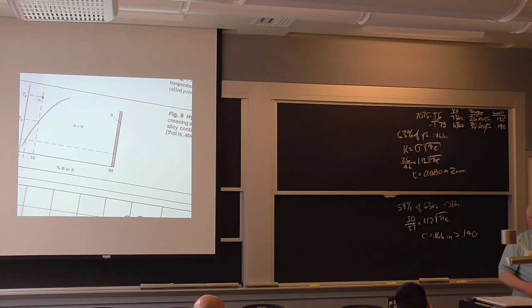If you just change over heat treat to get better corrosion resistance, better toughness, but lose yield strength, increase the wall a little bit. Hey, we're adding weight, sorry, if you want to be fail-safe, sometimes you have to trade off, right? But there it is, I can have leak before break.